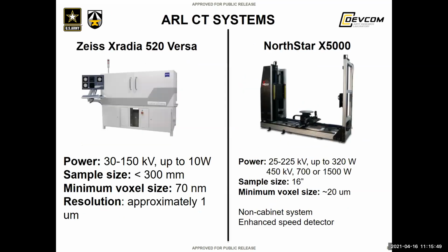So our CT systems allow for an easy non-destructive evaluation, which is very beneficial in the processing parameter development process, because say you have 90 samples, since you're testing out a wide array, it takes a lot of time to cross-section, mount, and polish, and then optically characterize these samples to look at the defect analysis. With CT, we're able to do one sample in under 30 minutes, if not less. It's obviously dependent on the material choice because it's density based, as well as the overall size of the object.